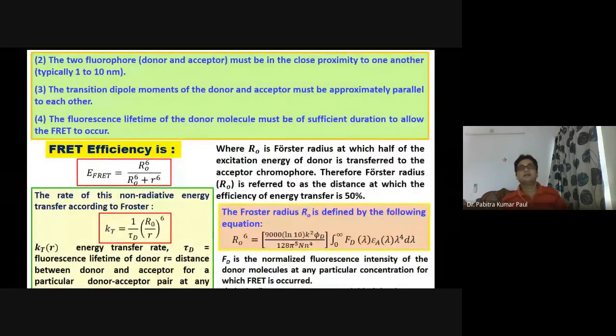The second one is that the two fluorophores must be in close proximity to one another. Depending upon the concentrations of the acceptor and the donor, the distance between donor and acceptor should always be 1 to 10 nanometer, that means 10 to 100 angstrom. Otherwise, collision will occur. If we increase the concentration of the solution too much, then collisional quenching will be there, and that is also a non-radiative process, and it can adversely affect the fluorescence energy transfer.